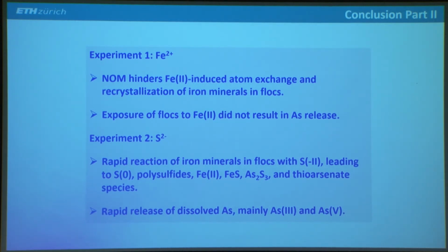Maybe it would if we would go much higher in concentration, but we wanted to stay at environmentally realistic concentrations. But we showed in the second experiment that flocs are very reactive with respect to sulfide. And so if we spike sulfide, we rapidly form elemental sulfur, polysulfides, iron-2. If there's enough sulfur, we will precipitate mackinawite and even orpiment, and also find some thioarsenate species in solution. And the result of this is a rapid release of dissolved arsenic.